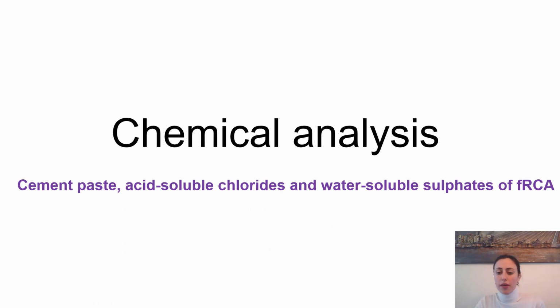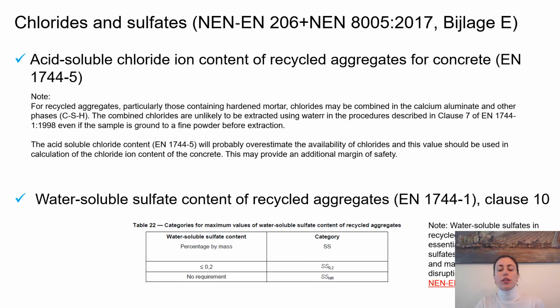In terms of chemical analysis, here we studied chlorides and sulfates according to the standard. However, the amount of material given by the standard is not followed, because we cannot use, as we are used to doing when checking chloride content from chloride contaminated concrete, a small sample. We need a larger sample weight in order to have representative values of contaminants, chloride and sulfate, since they are present in a very low amount anyway in non-contaminated concrete, or not there at all.